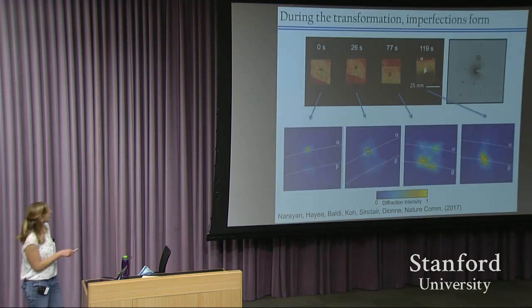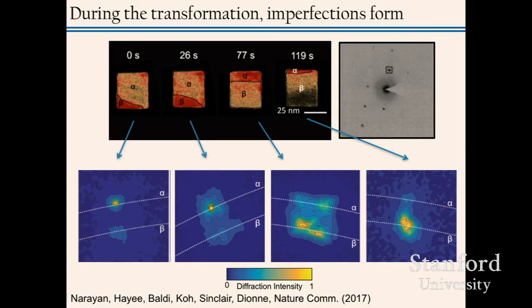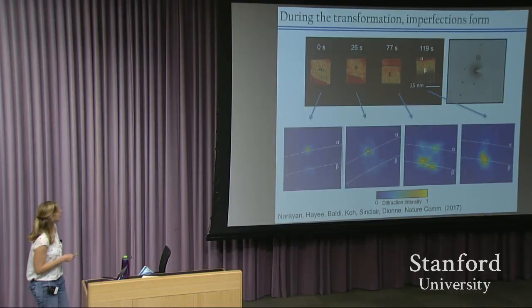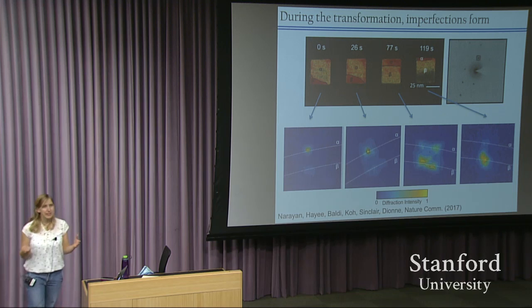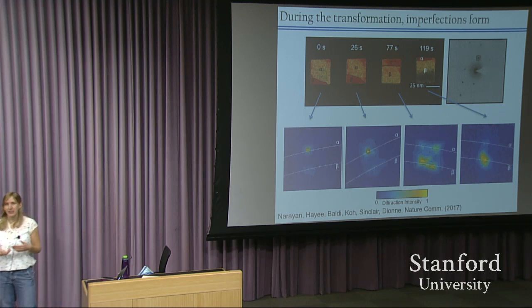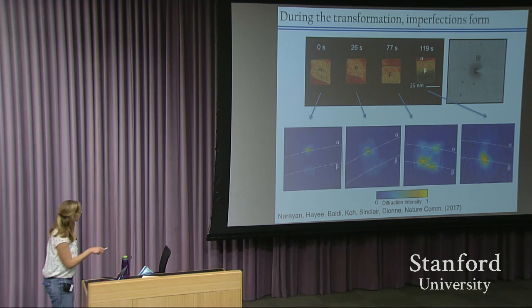So in addition to looking at these STEM movies that tell us how hydrogen is intercalating into the nanoparticle, in a nanocube basically entering through a corner and then reorienting itself from this diagonal interface into something that's straight across, and then pushing the old phase out through a diagonal, we can also look at diffraction patterns. I mentioned that this was a single crystalline nanocube. And when we introduce hydrogen, that new phase has a different lattice constant than the alpha phase. So we can rely on diffraction.